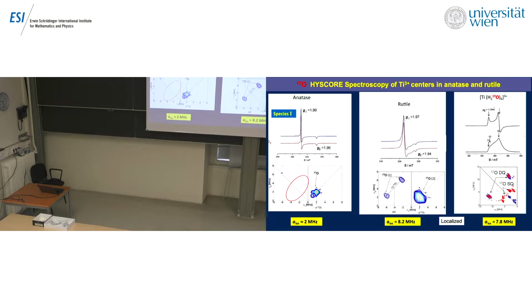I guess, I think, but I'm not sure because I can't measure this, that the normal lattice site, main site, in rutile is probably the same, but there is no echo, I cannot do that. But the amazing result is here. In the case of anatase, our strange regular axial spectrum, there is no interaction visible at all. What we see in this quadrant is something that is probably of the order of 2 megahertz, so much less than in the case of a strong localization. Does this mean an even higher localization? No, this probably means delocalization